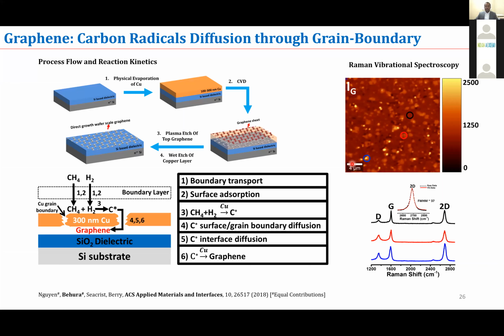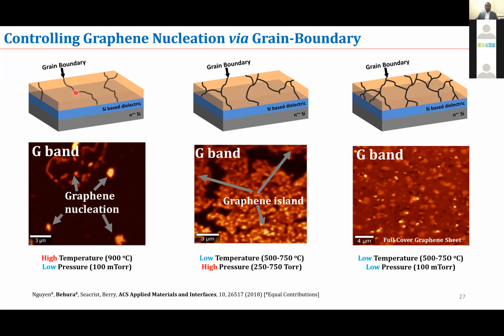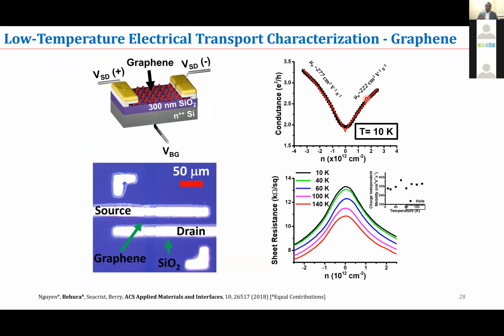And here is a mapping of the graphene that is formed directly on the silicon oxide, which shows a continuous graphene structure on the substrate. And to further optimize the process, you can control the number of grain boundaries by annealing these substrates. And you can see here that graphene, in the beginning, when you have fewer grain boundaries, started forming as nucleation points. And then you have small islands with optimum grain boundaries, with larger grain boundaries. If you have a decent number of grain boundaries, then we have a continuous graphene formation directly on the silicon oxide substrate. And then it is equally important to understand the electronic transport of these structures.